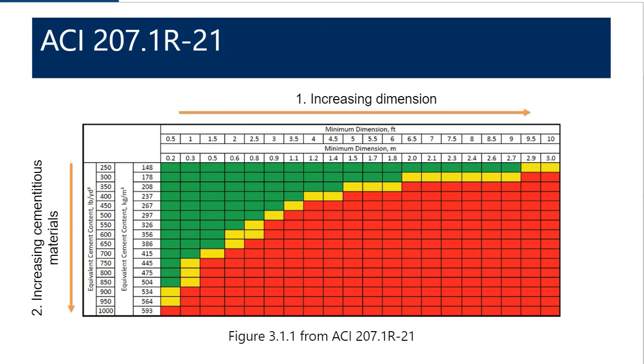Combining these two ideas, ACI 207.1 has also published this new table, which is pretty nifty. And it shows how increasing the dimension and increasing the total amount of cementitious materials interact with one another. So the dimension is increasing going from left to right, and the amount of cementitious materials in the concrete is increasing going from top to bottom. Any square that's shown in green is not going to necessarily require a thermal control plan, while anything shown in red will likely require thermal analysis or a thermal control plan. And then yellow is an in-between case.